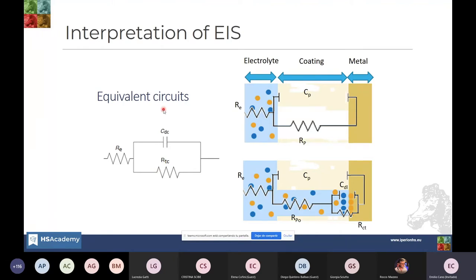And we have here in parallel two elements which represent the behavior of the corroding metal. In the top part we have a capacitor, which represents the capacitance of the double layer that is formed on the surface of the metal. And in the bottom, we have a charge transfer resistance, which is related to the charge transfer occurring for the reduction or the oxidation of the different species on the surface. Typically, the oxygen reaching the surface and being reduced, and the metal that is being oxidized.